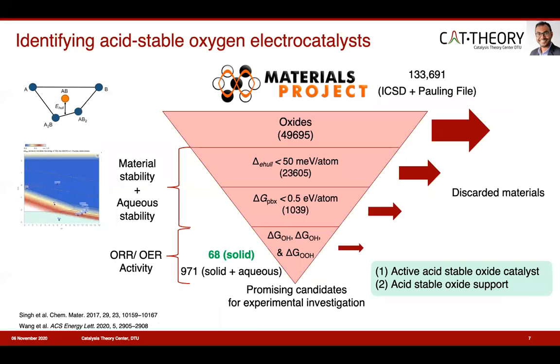In the first step, we narrow down the oxides from the Materials Project database, given that oxides are the most likely stable candidates under oxidizing conditions. Then to determine the stable materials, we use an Ehull criterion of 50 milli-electron volt per atom, which resulted in 23,605 stable oxides out of close to 50,000. Next, to identify acid-stable materials, we evaluated the aqueous stability of oxides at pH 0 and under typical potential ranges of OER, 1.2 to 2 volt versus SHE. We used the delta GPBX criterion of 0.5 electron volt per atom.